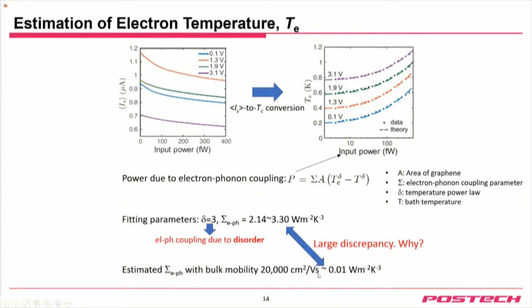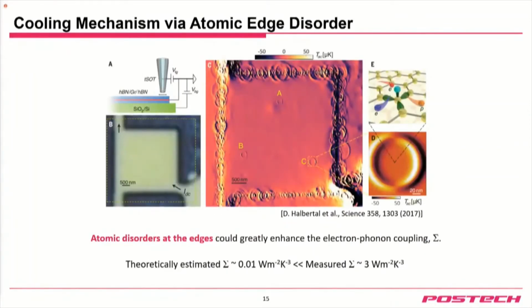So, the lower the electron-phonon coupling is, the more sensitive the bolometer would be, because energy doesn't dissipate fast. So the change of the electron temperature in equilibrium would be larger, right? So we want to know why this electron-phonon coupling is so big in reality compared to the theoretical value, to improve the sensitivity of the bolometer.